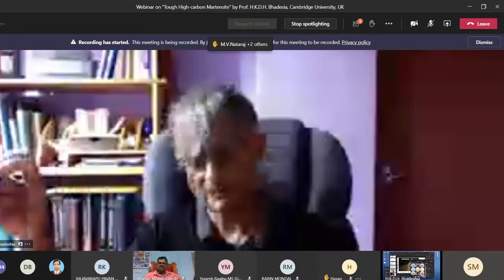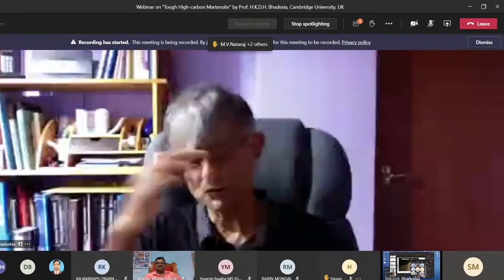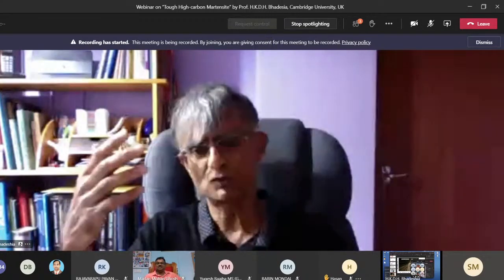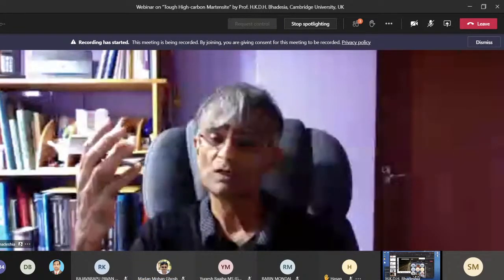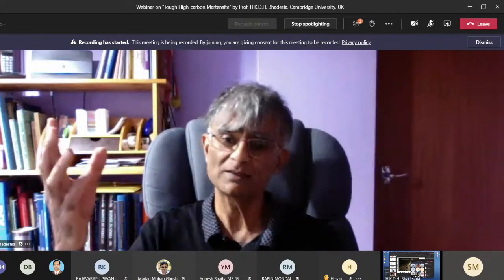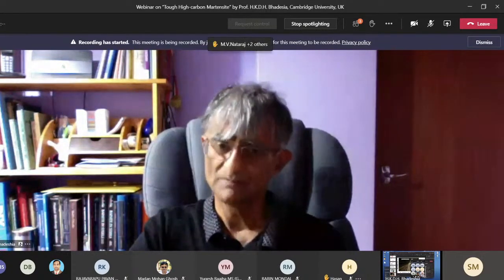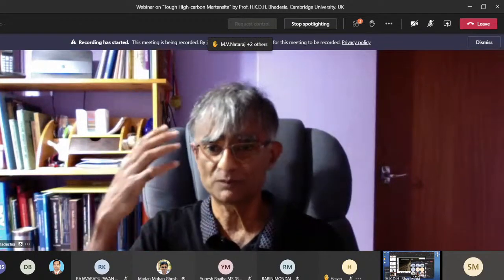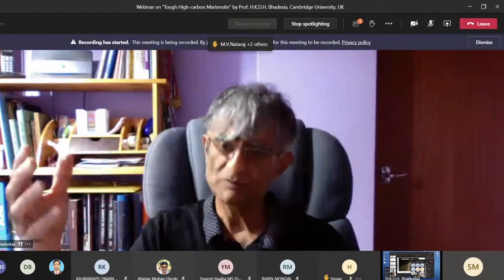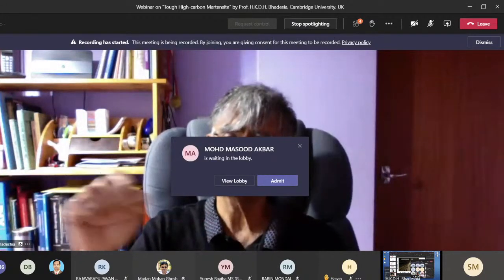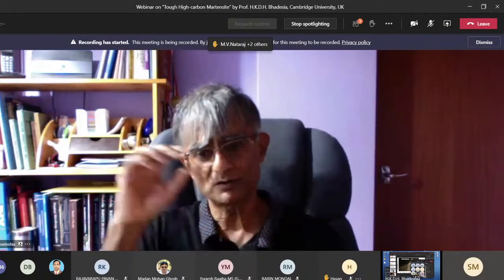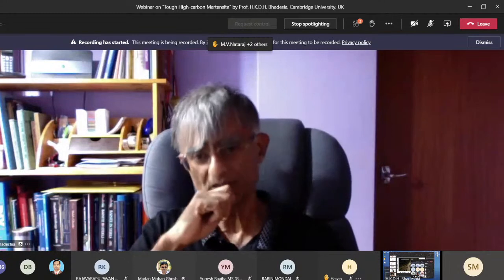Copper does not have the same effect, and it is possible that if we add too much copper, then we might get problems with the actual rolling from things like hot shortness. So one of the cures of hot shortness is that you add nickel, so that would kind of defeat the purpose. But I think that the basic concept is worth exploring. You could, in your laboratory, for example, make a sample in which you substitute nickel with copper and look at the basic properties as we did. Originally, we worked on something like 60-gram samples, and then scaled it up. So it's possible to explore it further as long as you maintain the martensite grain size extremely small.